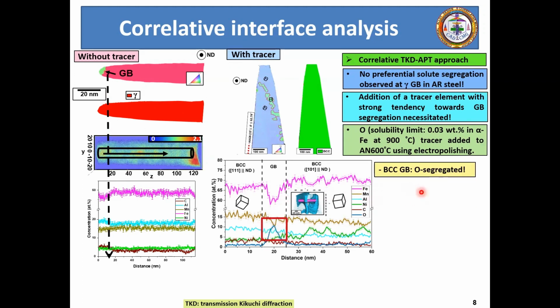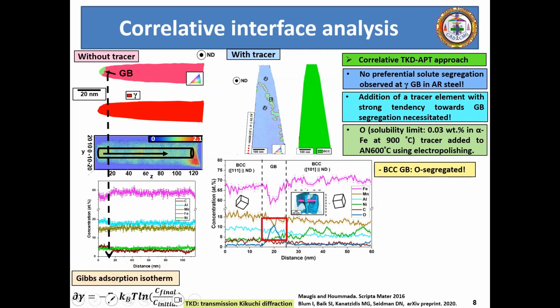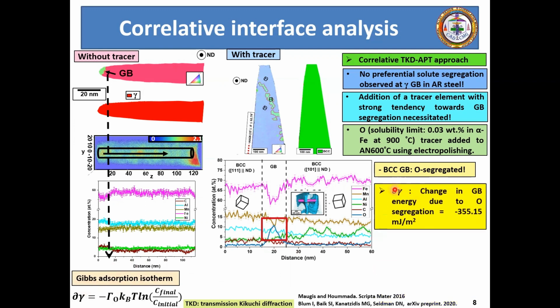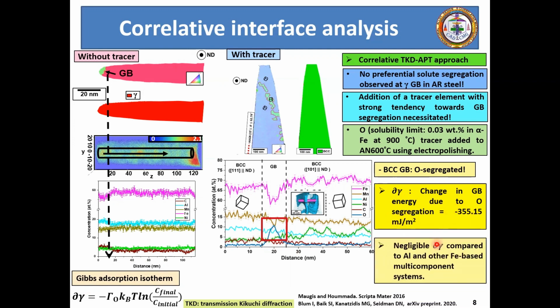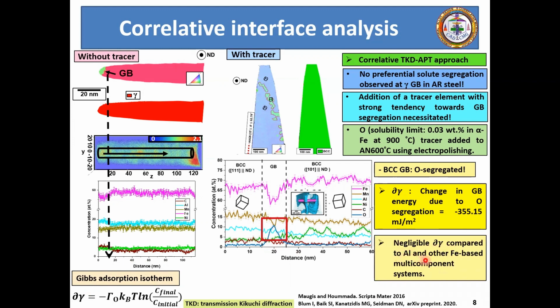So now, having seen this, we have used the Gibbs adsorption isotherm to find out the value of delta gamma, which represents the change in the grain boundary energy due to oxygen segregation at a BCC grain boundary, for example, and that's equal to nearly minus 355 millijoules per square meter. This magnitude of delta gamma is much smaller when compared to that of soft metals, for example, aluminium and even other iron-based multi-component systems. Now this implies that there is a negligible influence of different interfaces towards influencing the overall strengthening.